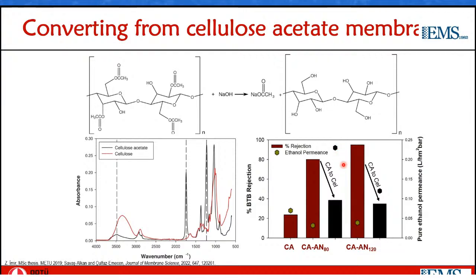Among other possibilities, we could finally attribute this to chain scission in the alkaline medium. And as an indirect indication of this, what we tried seeing was the following. We changed the reaction conditions, so the reaction duration and the alkali concentration, obtained cellulose membranes from cellulose acetate membranes, and then dissolved these cellulose membranes in the ionic liquid and looked at the viscosity of these solutions. And actually what we observed was that the more intense the reaction, either a higher duration or a higher alkali concentration, the lower the viscosity of these solutions, implying a shorter cellulose chain. So it seems that cellulose acetate nanofiltration membranes, when converted into cellulose, don't function as nanofiltration membranes.